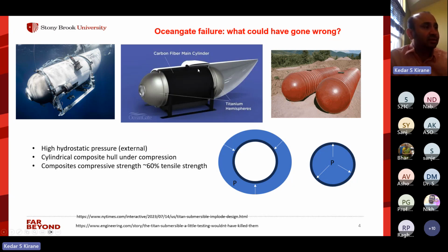So in this design, it was a little bit of a new design or a new concept where conventionally these kind of vessels are made from a titanium alloy, and the company OceanGate decided to now make it with a carbon fiber composite. So the overall structure was that there is a main cylinder at the center, made from the composite. Of course, the matrix was epoxy and the reinforcement was carbon fiber. And then there were two titanium end caps, and then the overall shape was like this, as shown here.